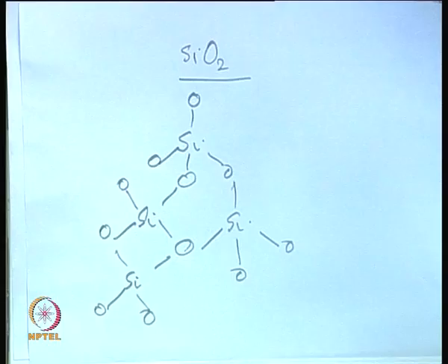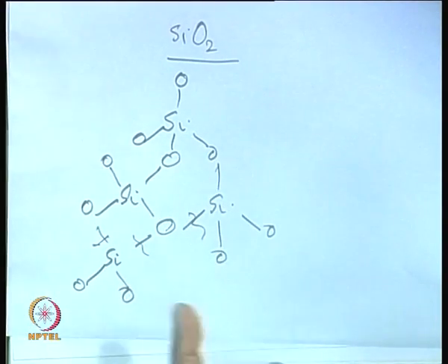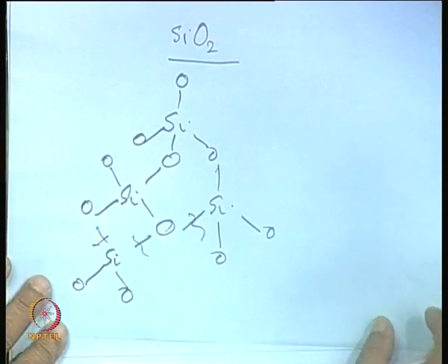So, in SiO2, there are these tetrahedral units attached to each other, so that the entire mass is actually one molecule in theory, and that is why molten silica is very viscous, because the flow unit is very large. Of course, if one raises the temperature too high, then many of these bonds will break thermally, so we make smaller and smaller flow units.